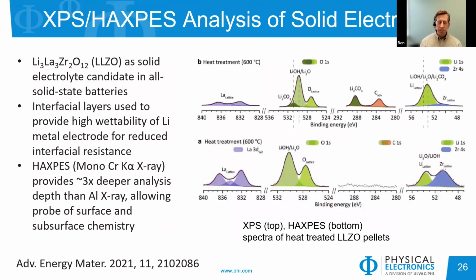Another aspect of XPS is to use a different photon energy, which will give you a different information depth. We talked about XPS with a soft X-ray giving maybe 5 to 10 nanometers information depth. Using hard X-rays, such as chromium K alpha X-rays, can give you a deeper information depth, about 3 times that of aluminum. So this is an example of looking at a solid electrolyte material, LLZO.